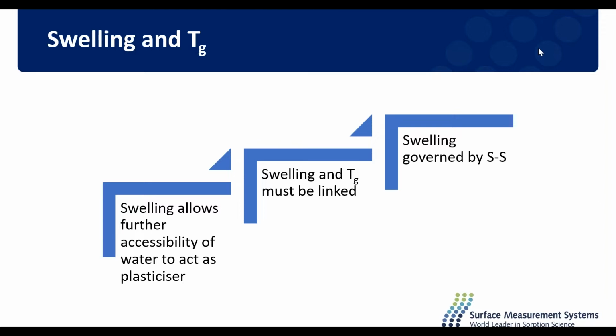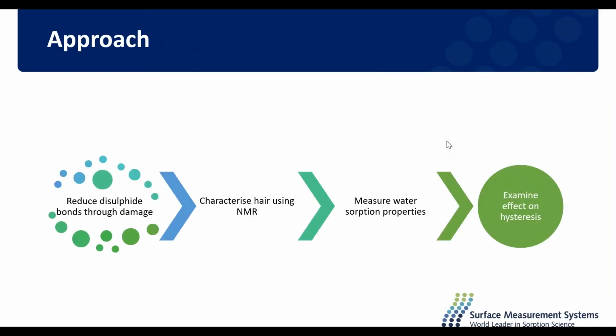Disulfide bonds are found throughout the hair fibre, and they are what causes its resilience and its strength. So if we want to affect the swelling properties of hair, we need to reduce those disulfide bonds. And that is what I've done in this project. So first, we reduced some disulfide bonds through damage. We then characterised our samples, measured the water sorption properties, and examined the effect on hysteresis.